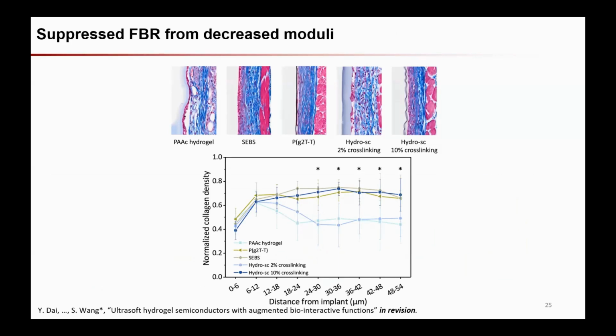Okay, so using this as the key material, we also further characterized the relevant immune compatibility, studying the modulus influence in the context of an electronic device. So what does that mean? In the electronic device, the semiconducting layer is usually a very thin layer on the surface. Then the question we asked is whether this very thin layer on the surface still influences the overall foreign body response. The result shows yes, and actually the influence is very big.